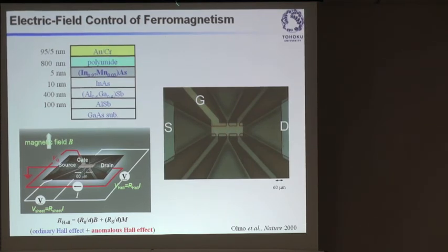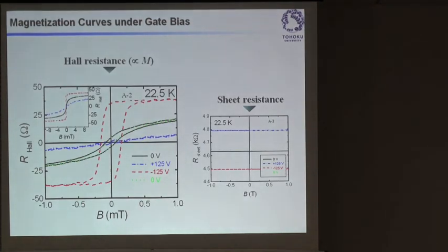Magnetization is probed by the Hall voltage, using the fact that the Hall voltage is dominated by the anomalous Hall term. So this is an example. At a temperature slightly below the transition temperature at zero gate bias, we see a very soft hysteresis, showing that the material is at the edge of the transition temperature, slightly below.